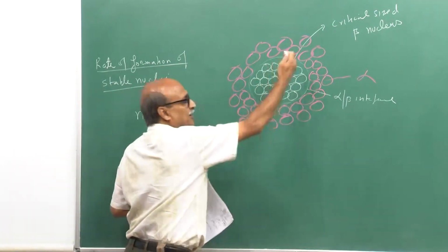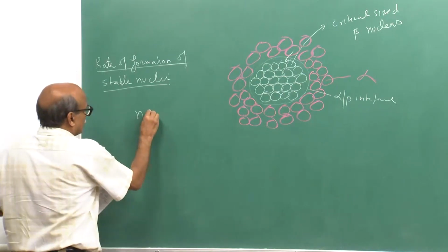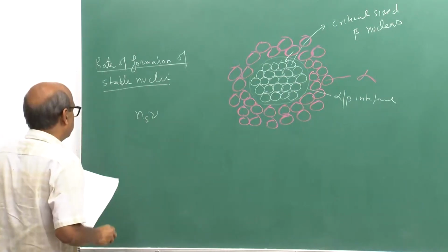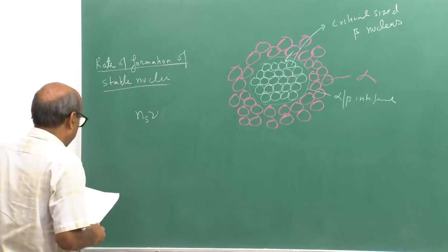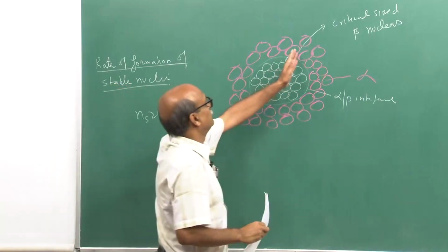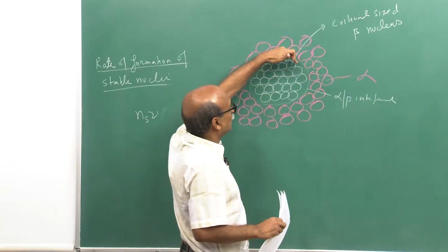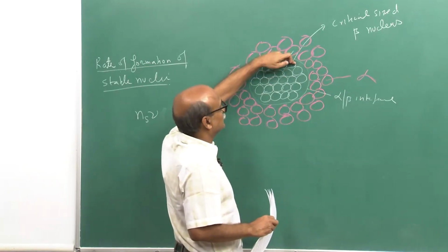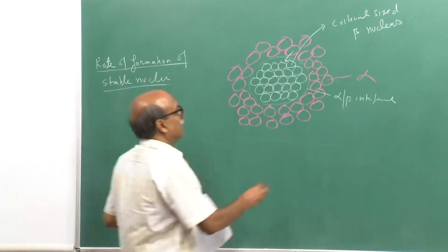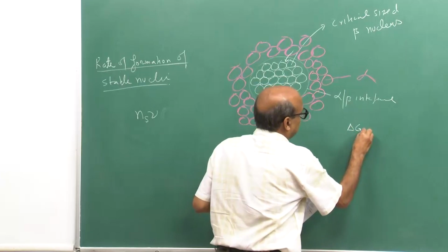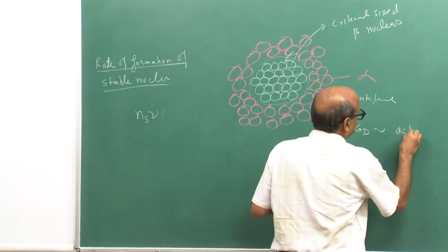All of these atoms are vibrating with a certain frequency called the Debye frequency. Multiplied by that frequency, multiplied by an activation barrier across which an atom from the alpha phase needs to go across the alpha beta interface to the beta nucleus, and that activation barrier is delta GD, the activation energy for the jump.